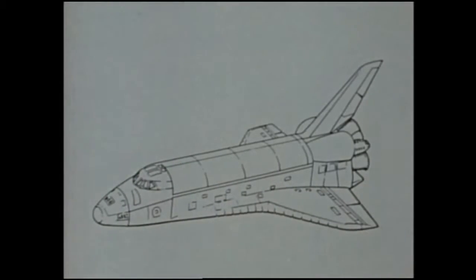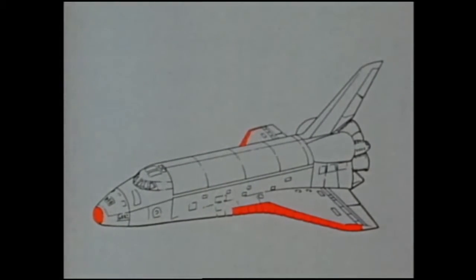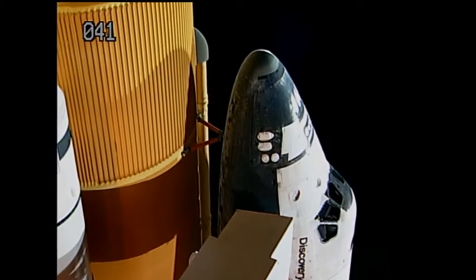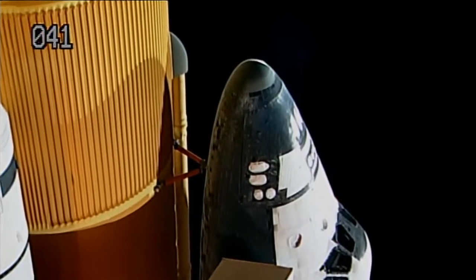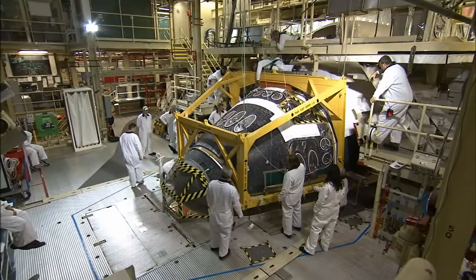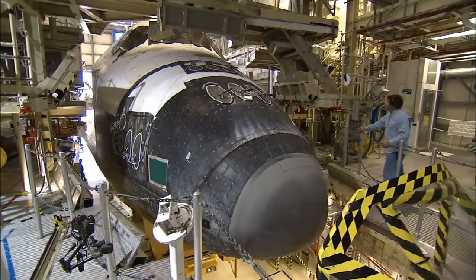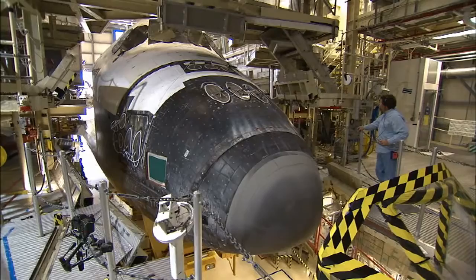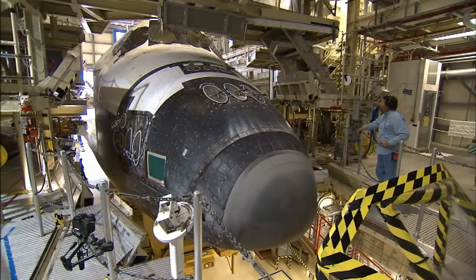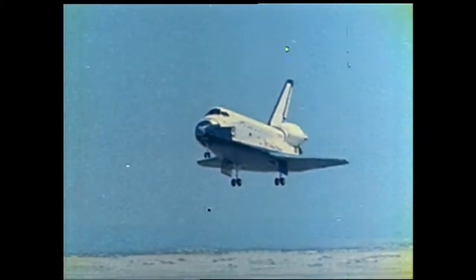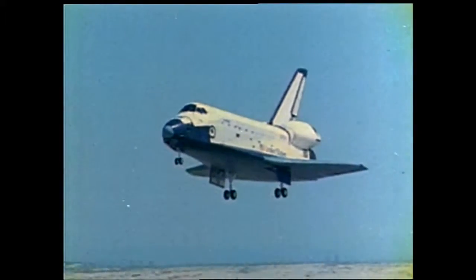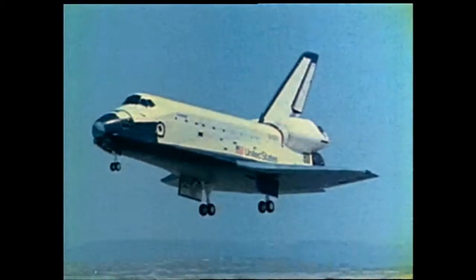Early on in the carbon program, we uncovered, along with some testing done at Ames Research Center, a phenomenon that we called oxidation between the coating of the carbon, which was silicon carbide coating, and the carbon substrate, which is basically carbon. We had what we call pinhole formations between the interface, which was not satisfactory because we could lose the carbon coating system due to lack of strength between the coating and the carbon silicon carbide coating. That was a very important finding between Ames and Johnson Space Center in ArcJet testing.